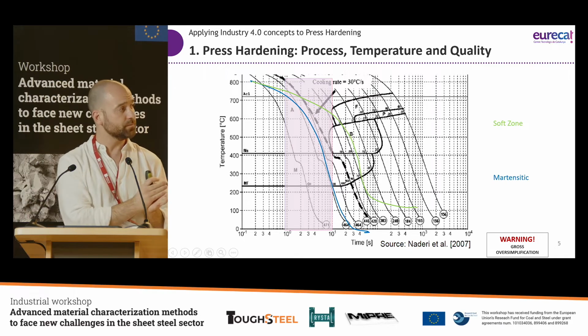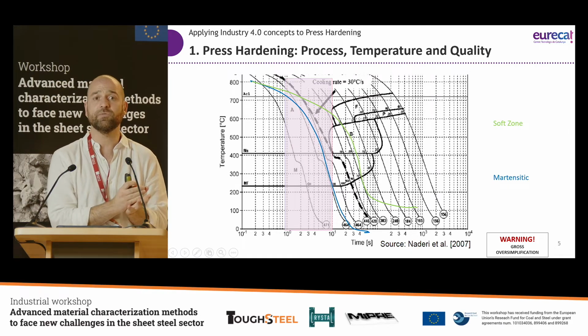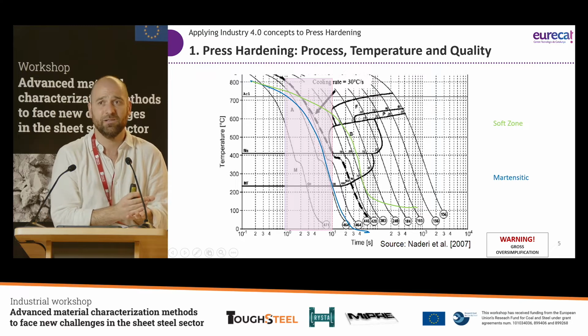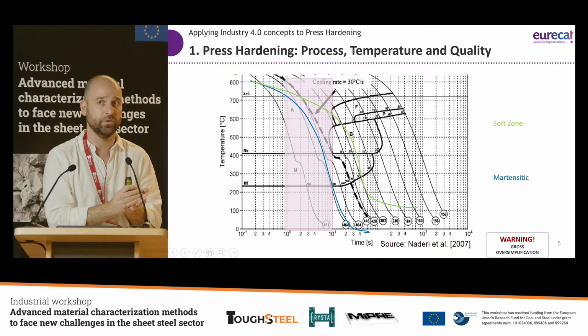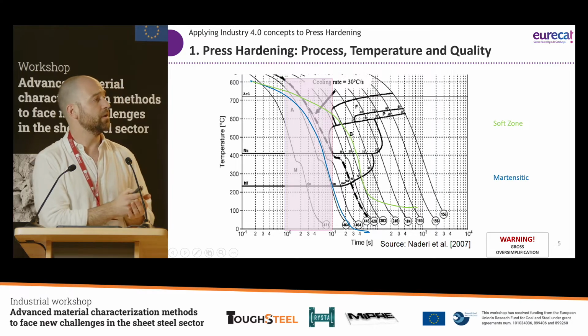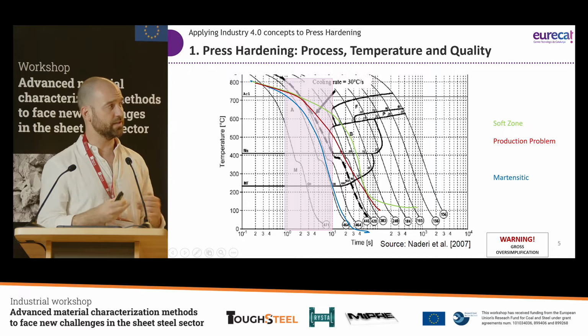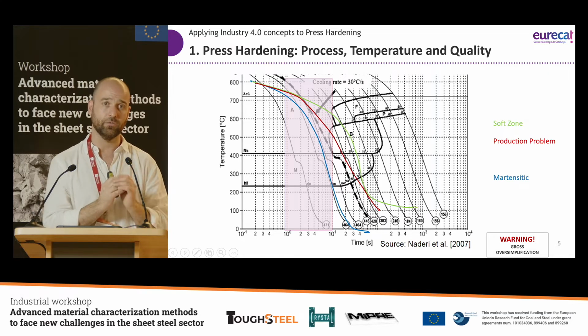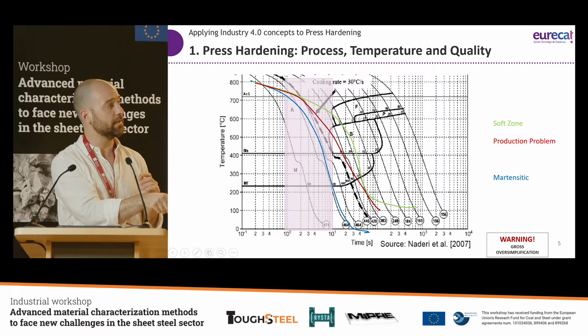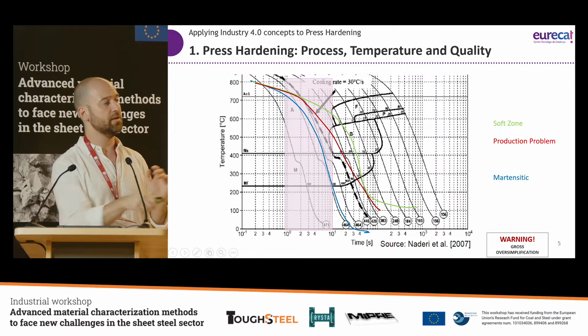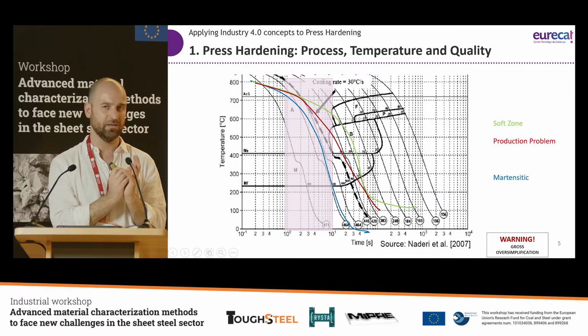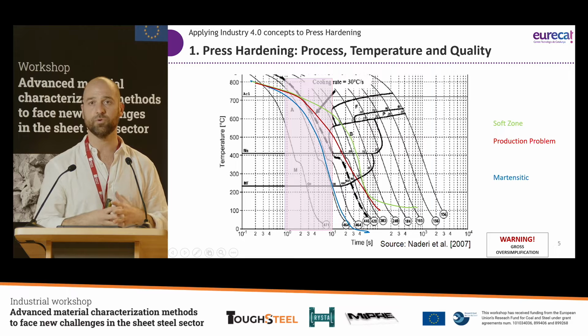And if you see, this kind of cooling is something that just does not happen in the process unless we force it or we do things very wrong. If we think about a process where the die has bad contact or we have a hot spot, it will look more like this. So if you see the window of time, we are getting 500 degrees for 110 seconds. This is more like what a not okay process would look like.